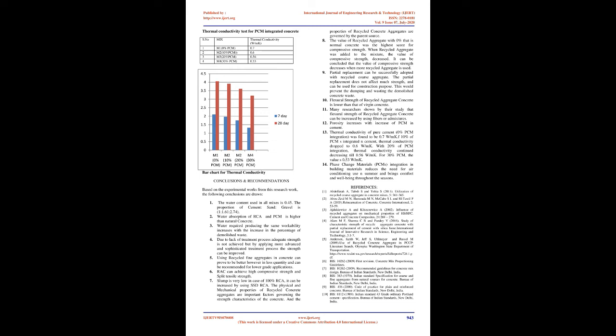Conclusions and recommendations. Based on the experimental works from this research work, the following conclusions are drawn. 1. The water-cement ratio used in all mixes is 0.45. The proportion of cement, sand, gravel is 1:1.61:2.74. 2. Water absorption of RCA and PCM is higher than natural concrete. 3. Water required to produce the same workability increases with the increase in the percentage of demolished waste. 4. Due to lack of treatment process, adequate strength is not achieved, but by applying more advanced and sophisticated treatment processes the strength can be improved.